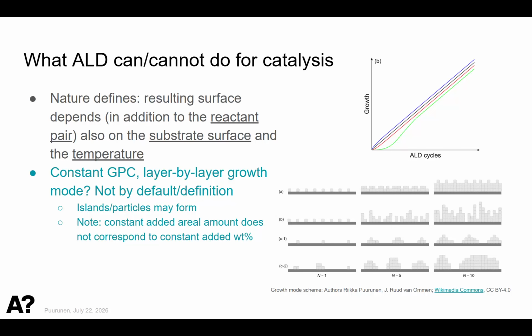There are quite some misconceptions around ALD. One is that you would get full monolayer growth per cycle. This was the expectation of Suntola, who already in 1974 learned that that's not the case. Still, people are often expecting that. It's almost never the case. For the review in Chemistry of Materials, we actually went through the growth per cycle values, and we found that the maximum that had been reported was 7 metal atoms per square nanometer, which corresponds to roughly half of a monolayer. Typically, it's a little bit less even.